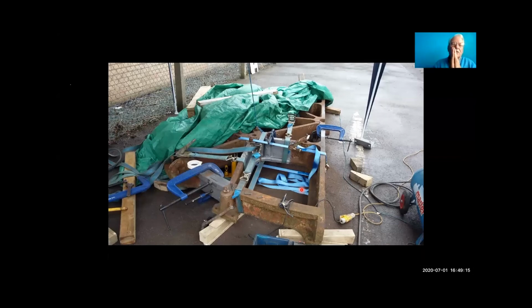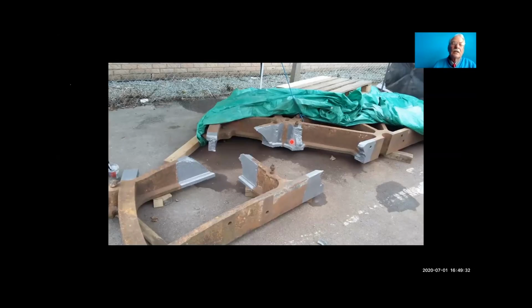If the crack is just a fine crack, you can't get anything into it to fill it. If you use an epoxy or something like that in this situation, you'll find that it's not strong enough. It will fix it back together, but you wouldn't be able to get sufficient strength in just one, two, three, four points to withstand the sort of heavy loads that this has to put up with.